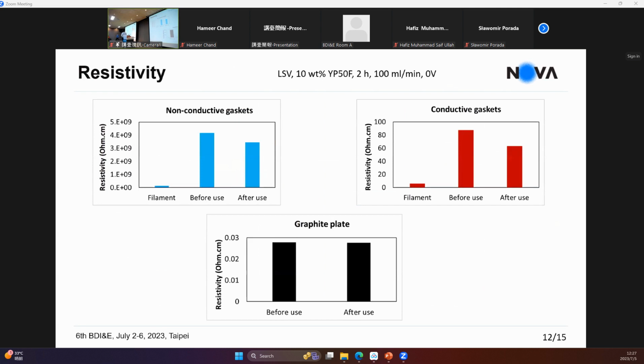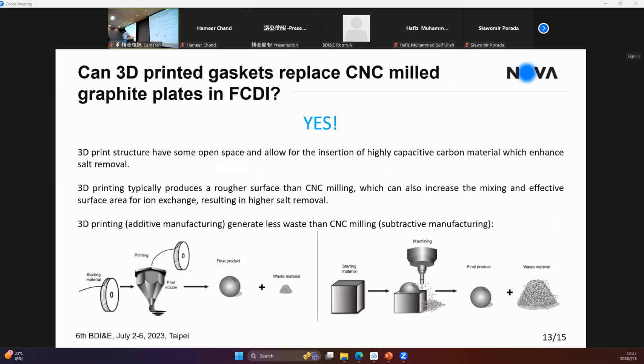And indeed, we measured the resistivity of the materials before and after use. And indeed, for 3D printed materials, it decreased. For graphite plates, it stays the same. So the answer to the initial question is yes, at least in our opinion.